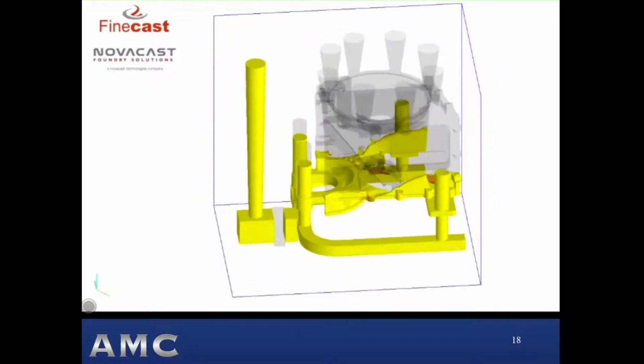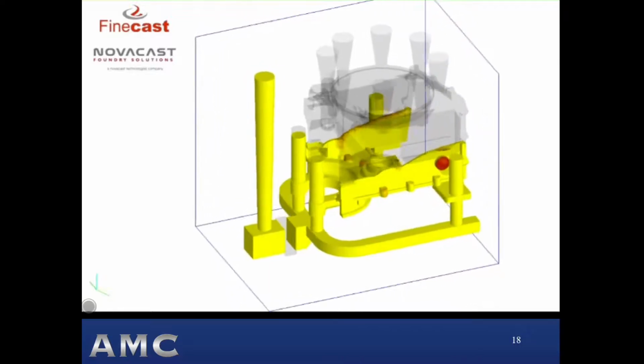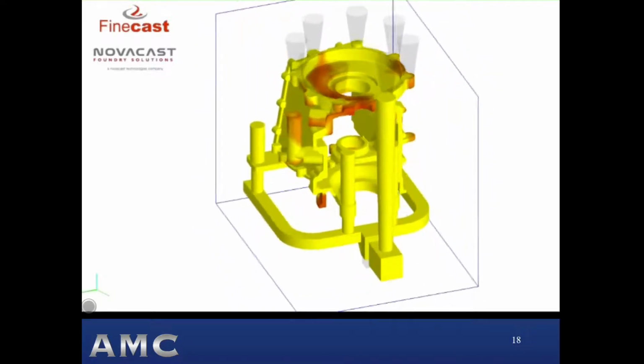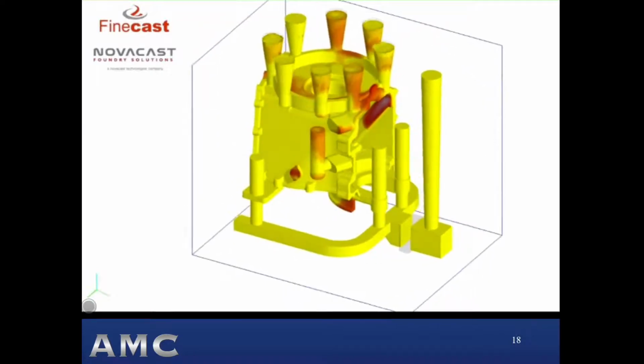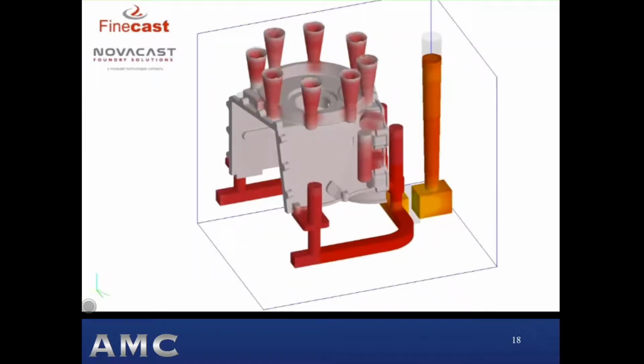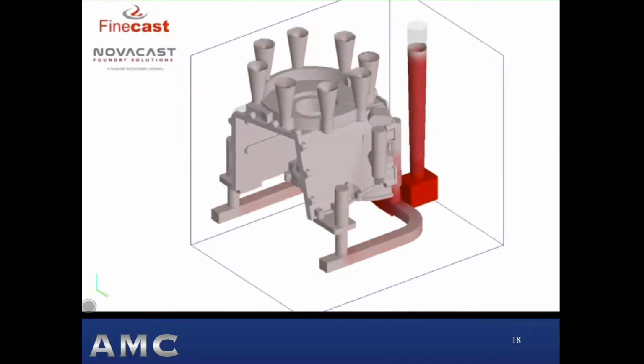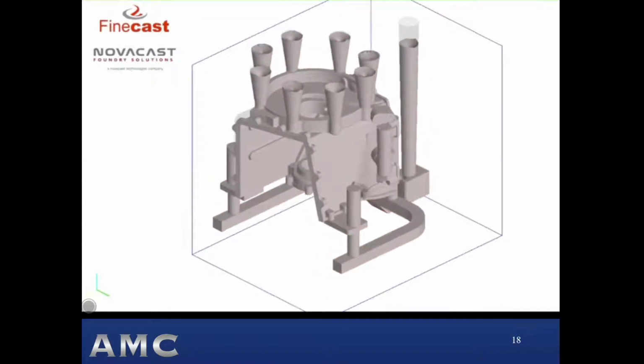So what we're seeing now is the mold cavity being filled, and you're seeing attachments to the mold cavity that enable the filling of the mold and also feed solidification shrinkage to achieve the mechanical properties that are specified. So all of these attachments that we see from the mold filling system, from the risers which feed solidification shrinkage, and even some surfaces like this may have a chill against it to help it solidify quicker. All of those surfaces aren't like the surface comparator that we just looked at.